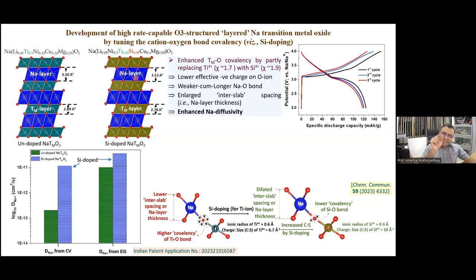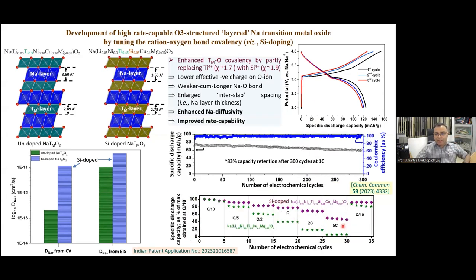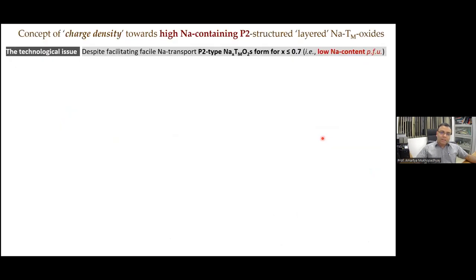But then, based on the same concept, we can go the other way slightly, and we can tune the interslab spacing to get back the rate capability without hampering the water stability to a significant extent. So for the same reason, we replaced a little bit of titanium 4+ with silicon 4+, having a greater charge to size ratio, to enlarge the interslab spacing to a little extent, and then improve the rate capability drastically without hampering the water stability. So this material has an excellent rate capability, as one can see, while maintaining the water stability. Now,